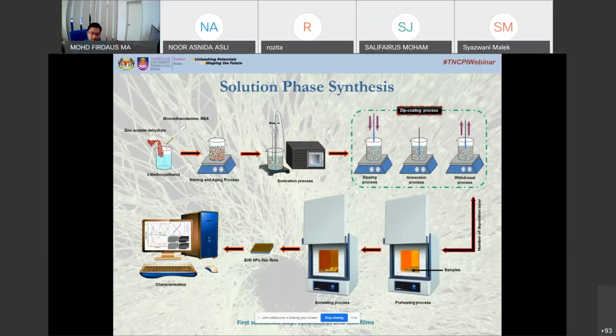This needs to be considered and synthesized on top of the substrate before the synthesis of the nanowire. As you can see here, these are the precursors being used. We also introduce a sonication process to enhance the homogeneity of the solution. Then in this case, we are using the dip coating process. We are also doing spin coating, and then it goes for preheating and annealing temperature for the development of the seeded catalyst layer.